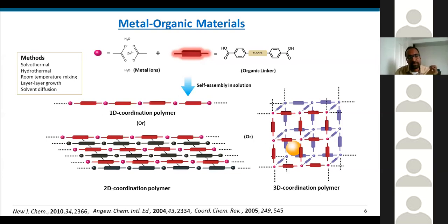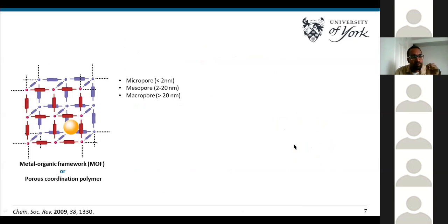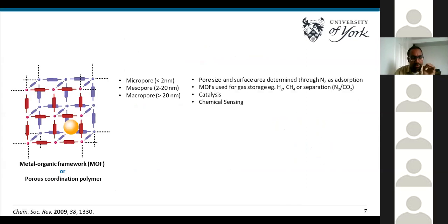My work is basically creating these MOF structures at the nanoscale, not at the crystalline scale. MOFs are porous materials that possess defined cavities and a definite surface area. The cavity size or pore size and the accessible surface area we can determine using nitrogen gas adsorption. Depending on the type of adsorption profile you get through nitrogen gas adsorption isotherms, they are classified into microporous, mesoporous, or macroporous.